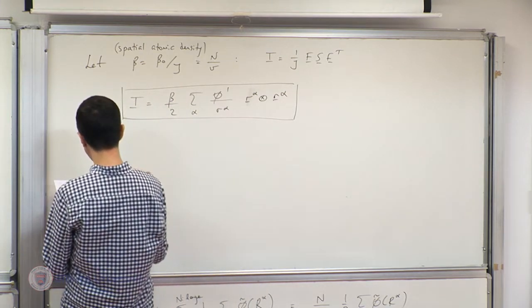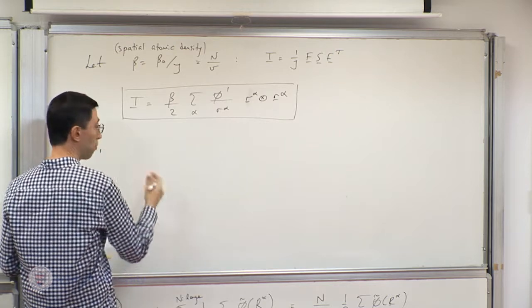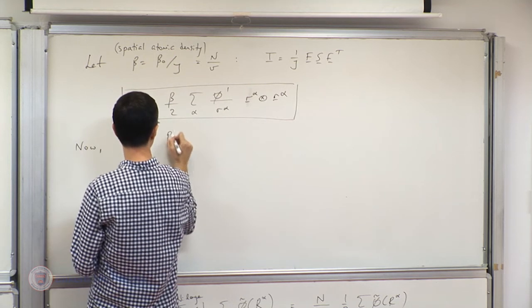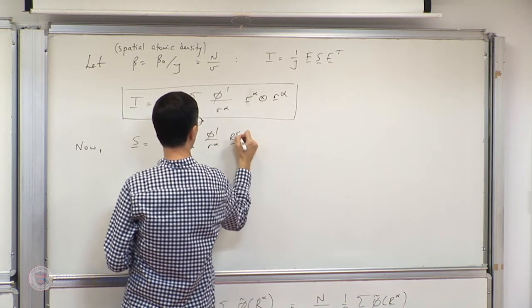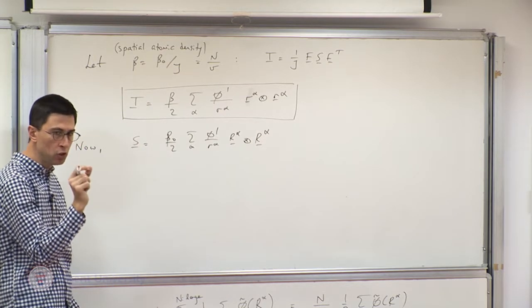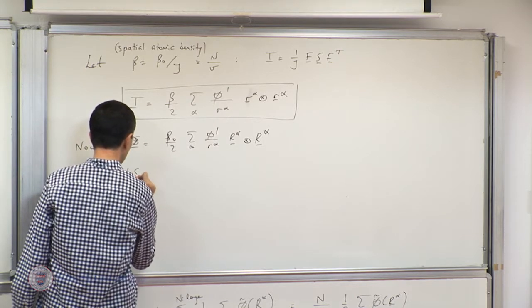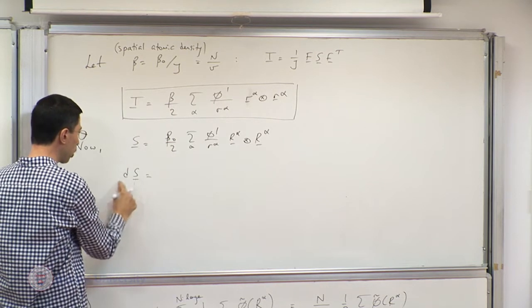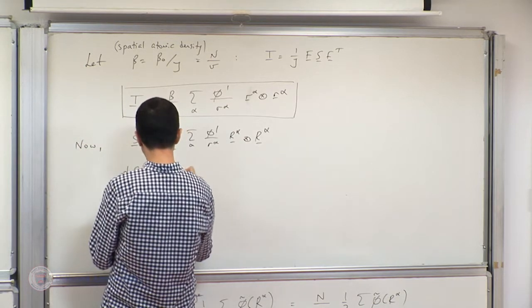Let's try to extract some elastic constants. Referring to the second Piola-Kirchhoff stress tensor — beta-naught over 2, sum over alpha, phi-prime over r_alpha, tensor product capital R_alpha otimes capital R_alpha — I am going to increment the deformation a little bit. When the deformation is incremented, the stress will be incremented accordingly. This small change in stress due to a small change in deformation is ds = (ds/dF) dF.